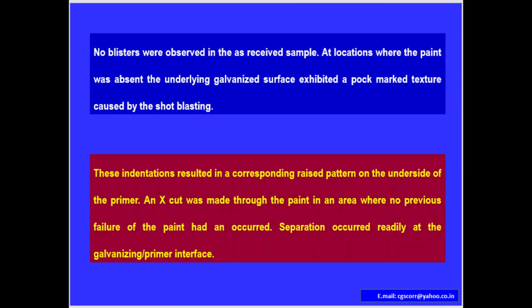At locations where the paint was absent, the underlying galvanized surface exhibited a pock-marked texture caused by shot blasting. These indentations resulted in a corresponding raised pattern on the underside of the primer. An X-cut was made through the paint in an area where no previous failure of the paint had occurred. Separation occurred readily at the galvanizing primer interface.